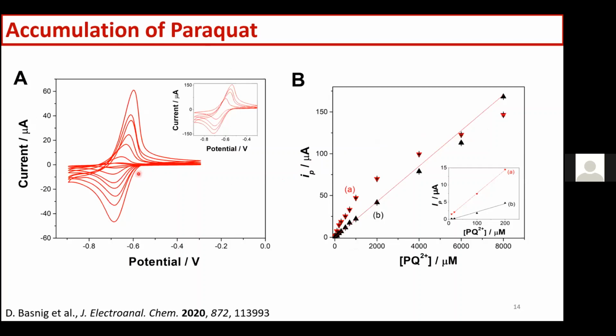And then we did this for a series of concentrations ranging from 10 micromolar up to 8 millimolar of paraquat dissolved in the solution, and we could see that at the low concentrations we were always having a greater signal for the modified electrode than for the bare electrode, suggesting that we were pre-concentrating the paraquat inside the film. Then reaching the higher concentrations between 2 and 8 millimolar, we were getting close to the signal of a bare electrode, suggesting that the amount of free paraquat that was diffusing freely through the films was significantly greater than the amount of paraquat that was absorbed on the silica.